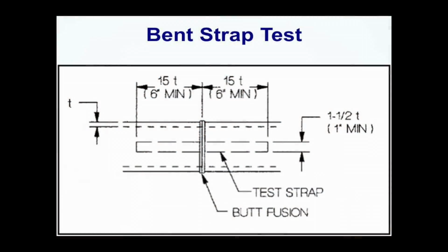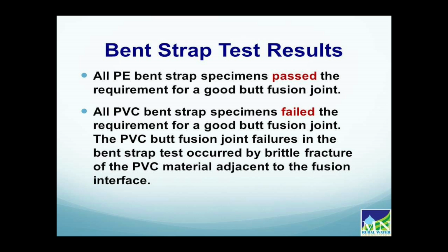The first test that was done is called the bent strap test. Basically, you take a strap, about a minimum of an inch wide, several inches long, with the butt fusion in the middle. You then take the strap and bend it. All of the polyethylene fusion bent strap tests passed the requirements for a good butt fusion joint. All of the PVC specimens failed the requirements for a good butt fusion joint. The butt fusion failures in the bent strap occurred by brittle fracture of the PVC material adjacent to the fusion interface, so they did not pass that particular test method.